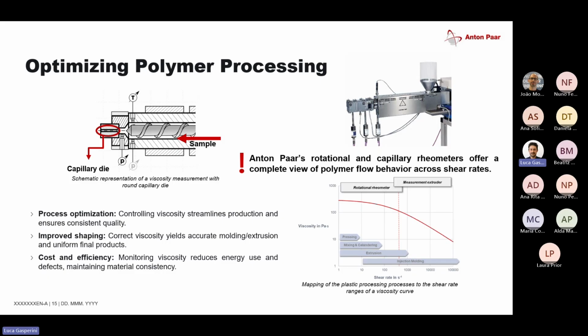This comes in two geometries, a slot capillary die and a round capillary die. The round capillary die usually is able to cover higher shear rates, since it's a lot thinner, but has a drawback: you need more measurements in the end due to an additional correction, since you cannot measure, with our transducer, the pressure inside of the small round capillary.